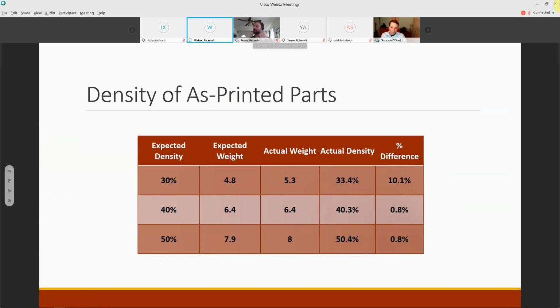The table shown here represents different densities for our printed samples. We have three different densities that we tested: 30%, 40%, and 50%. This helps support the purpose of our project in terms of weight reduction while also maintaining our strength properties. The 30% relative density sample carries a weight of 5.3 grams, the 40% sample carries a weight of 6.4 grams, and the 50% sample carries a weight of 8 grams.